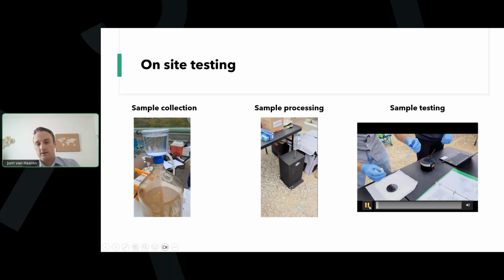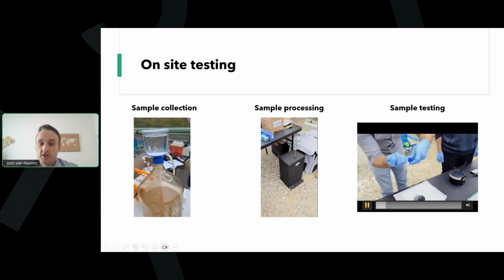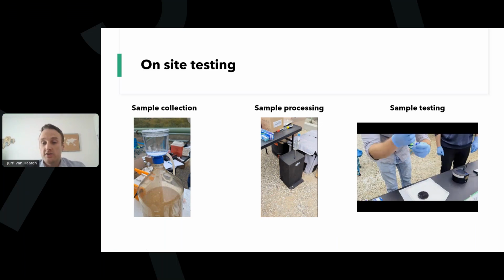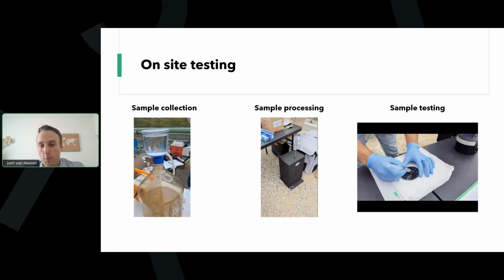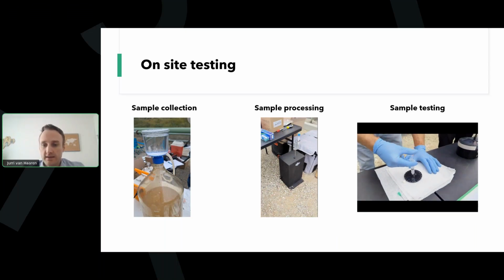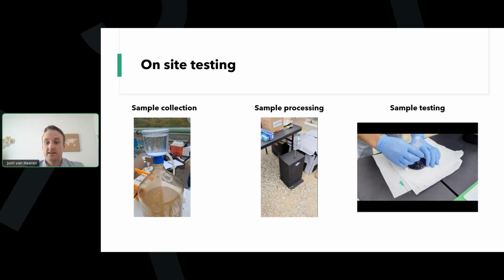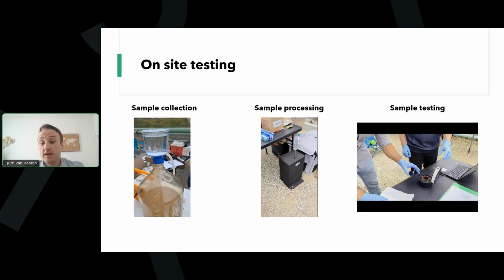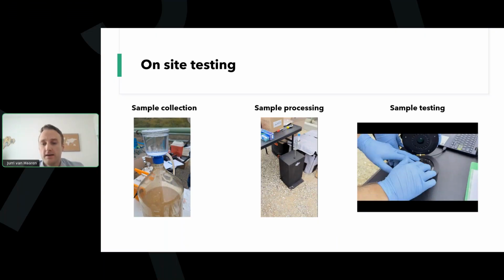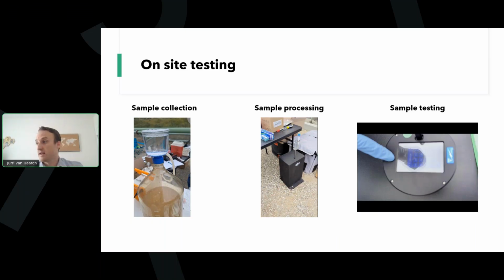After that shaking step, you draw up the sample into a syringe, and then you use that syringe to deposit the sample into the cartridge, and then it immediately dissolves the beads. So the assay is then ready to go. You take your cartridge, put it into the amplification device, and as soon as you close the lid, it automatically starts running, and then within 30 minutes, it tells you exactly what microbes are there. So super straightforward process, right? As you can see from these videos, it's a bit messy still, so we're still looking to optimize the process and make it as easy to use as possible, but it works really well already.